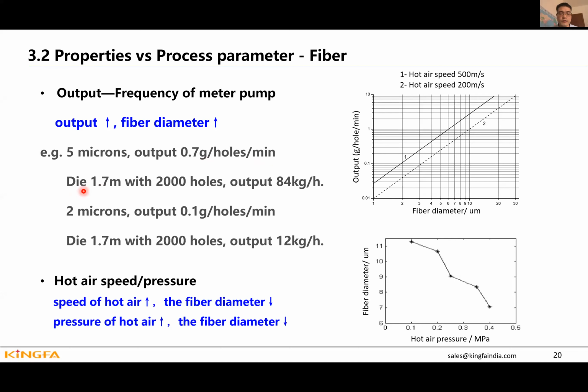If we have a die whose width is 1.7 meter and has 2,000 holes, then the output is 84 kg per hour. But if we want to make 2 micron, then the output is about 0.1 gram per hole per minute, and the output comes to only 12 kg per hour. So by this figure, we can calculate our output and the final fiber micron we can get.